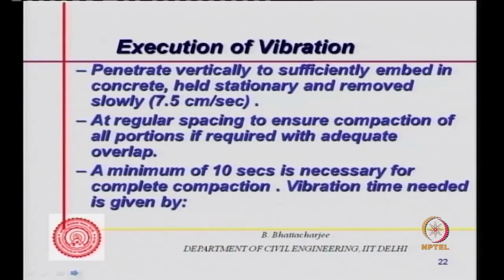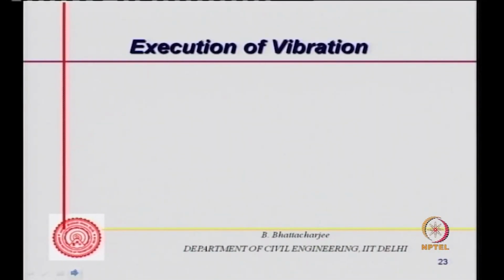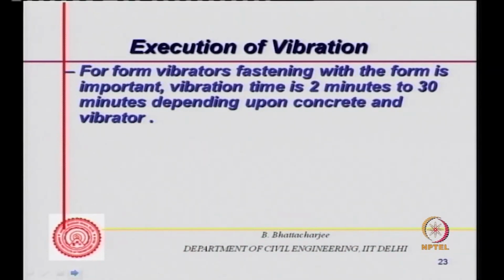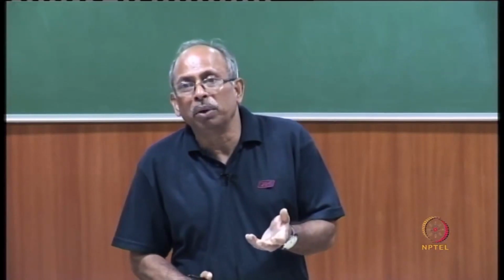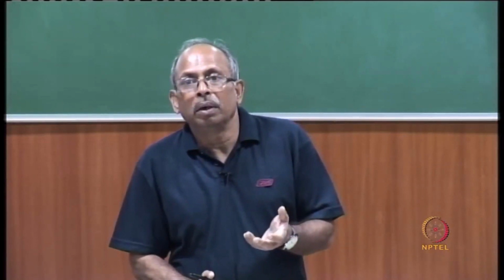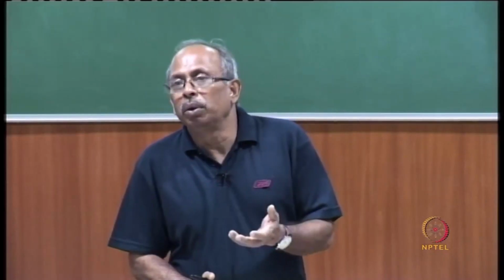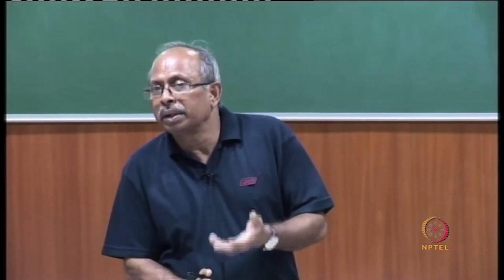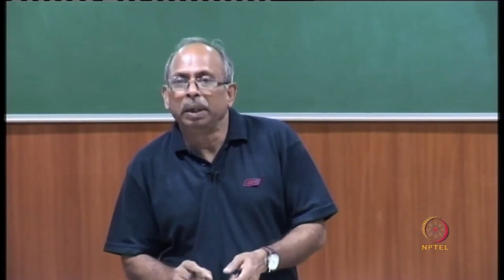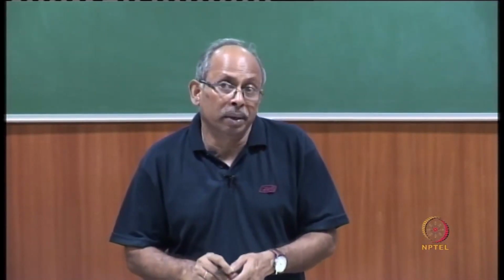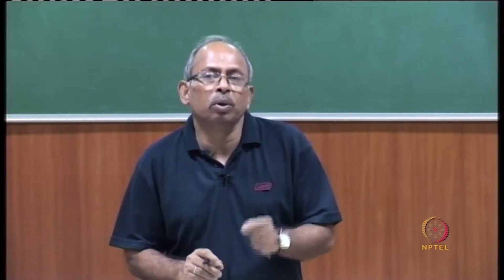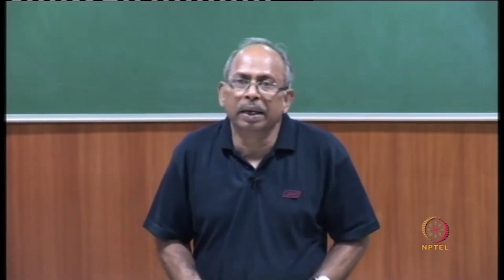A minimum of usually 10 seconds is necessary for complete compaction. Vibration time needed is given by some equation, but I am not talking about that because nobody is going to use equations much. But we understand that at least 10 seconds if you keep it, and when you see the mortar has come out, you pick up the needle vibrator, just lift it up slowly at a very slow velocity, and you can see the slurry right at the top.